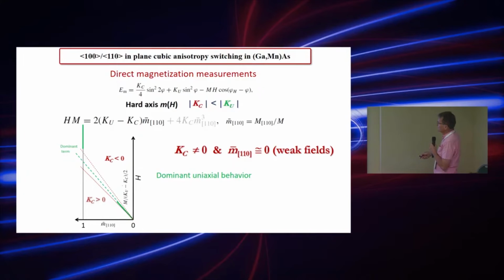And this time, please note, the slope is just given by the difference between the anisotropy constants. So that line, as you see, starts at a different angle, a different slope, depending on the sign of the cubic anisotropy. So indeed, the sign of the cubic anisotropy changes something. It modifies the magnetic response, but only at this particular orientation that I showed experimentally. And now, to get the full expression, we are switching on this term, and this term means that for a positive value of Kc, we get positive curvature, so we should go like that, and for a negative value, we certainly should go like that.